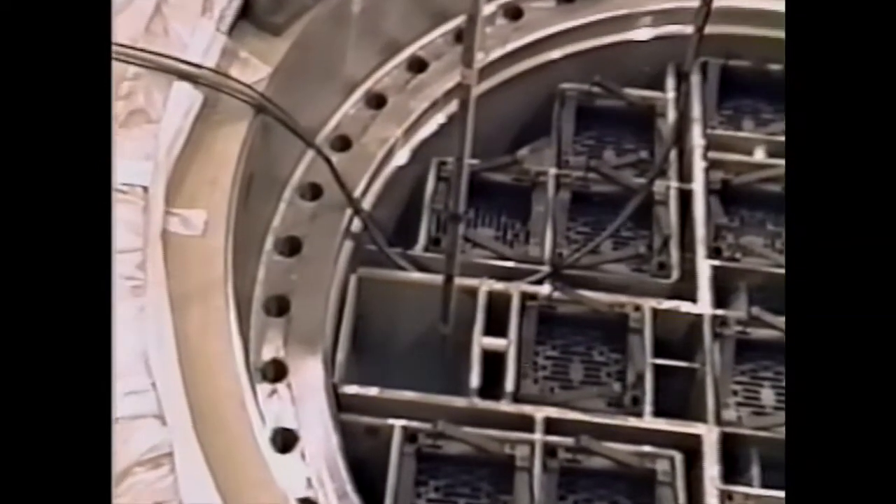Occasional exceptions were mineral stains left over from the cask dewatering in 1985, as seen at the bottom of the fuel tubes in the sequence. The only features on the fuel tube walls were the grinding marks, the machining marks, and welding discolorations from the original basket fabrication. In general, the cask and the basket surfaces had an as-milled surface finish that was bright and reflective, indicating that no corrosion had occurred. The general condition of the fuel tubes is shown by video sequences from several fuel tubes within the cask.